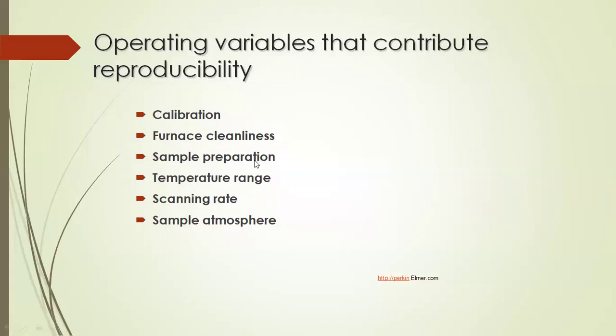Sample preparation. Always remember that your sample should cover the whole base of your sample holder. It should not be in a grain form. If you have a chunk of a polymer, cut it into small flat sample sheets and cover the whole bottom of your sample pan with the sample, because it will avoid the thermal lag, and whatever onset of degradation you get will be the true onset.